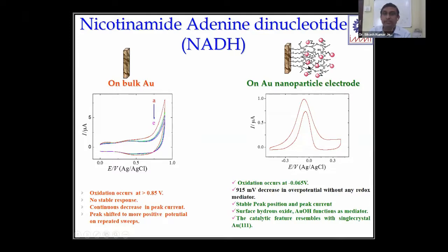So after modifying the electrode with gold nanoparticle, which is a very simple and easy way, we used some mercaptopropyltrimethoxysilane. That is a kind of silicate network having thiol groups, a 3-dimensional network we put on the gold electrode, and because of these thiol groups, we do self-assembly. We dip this electrode into the gold nanoparticle solution. The nanoparticle is self-assembled to the thiol groups, because gold-thiol has a specific interaction. That's why it is properly self-assembled on the electrode surface.